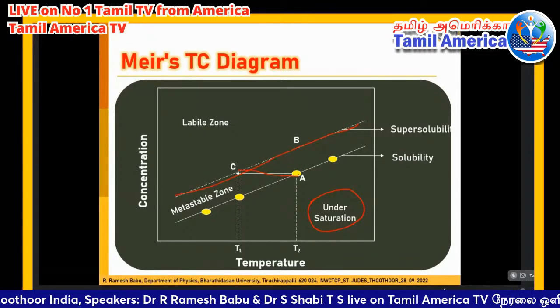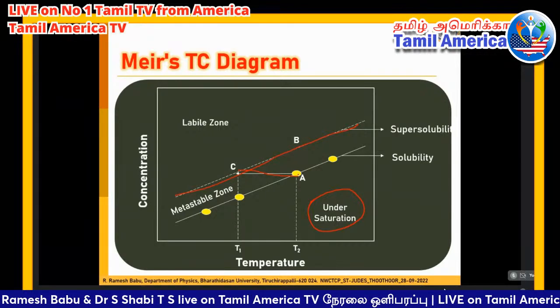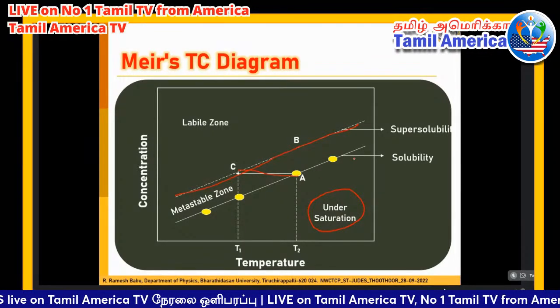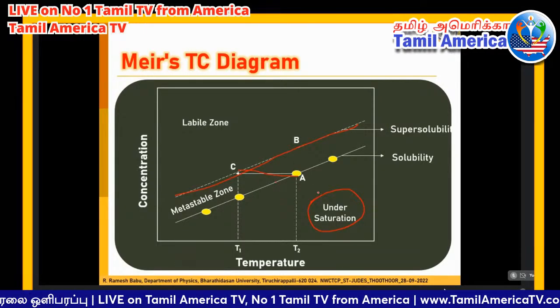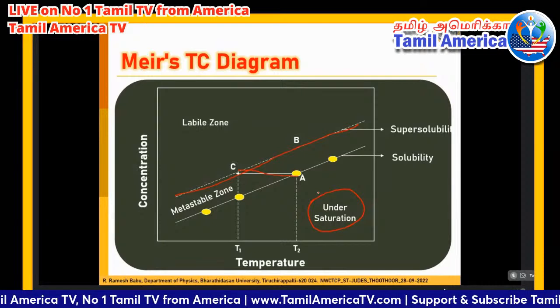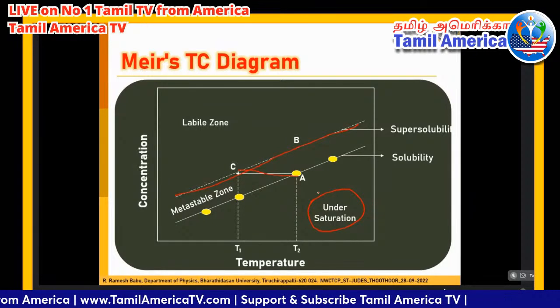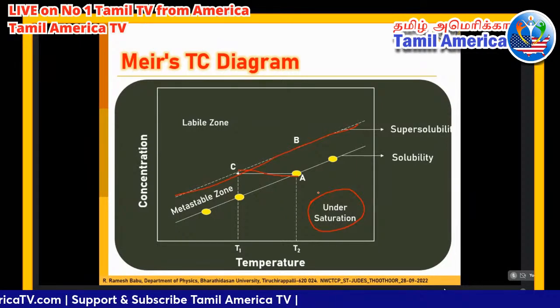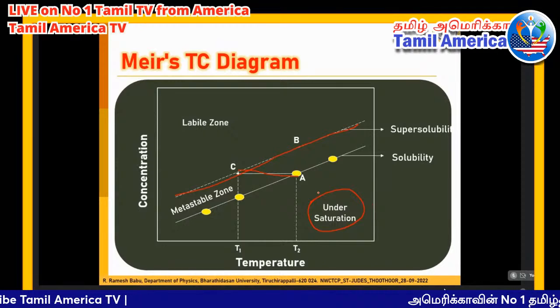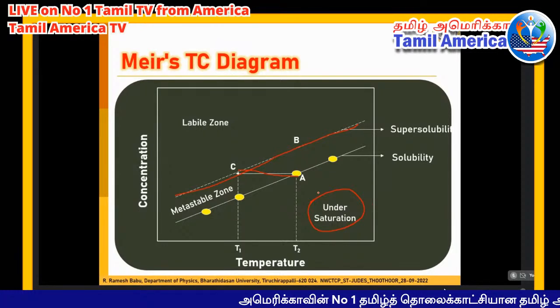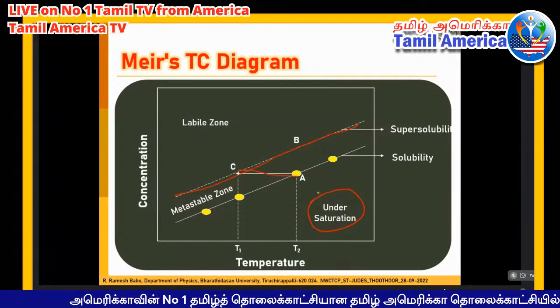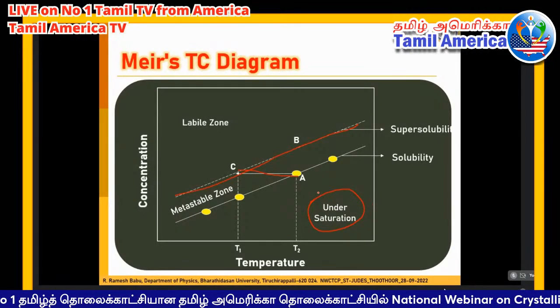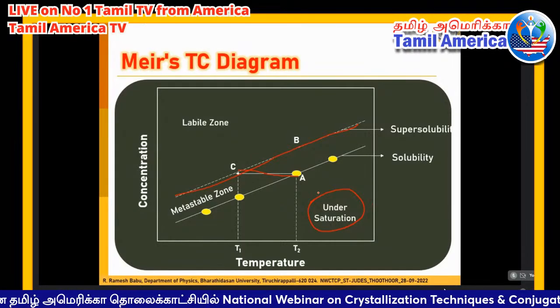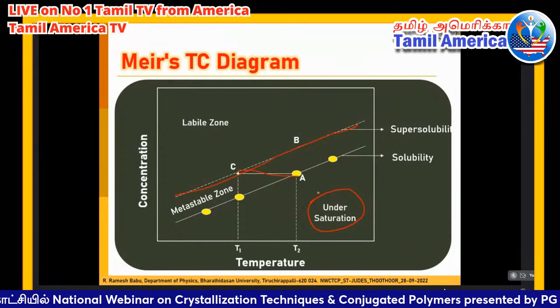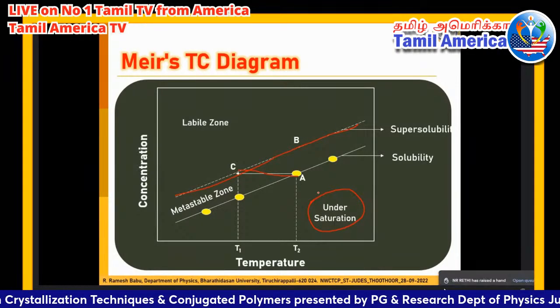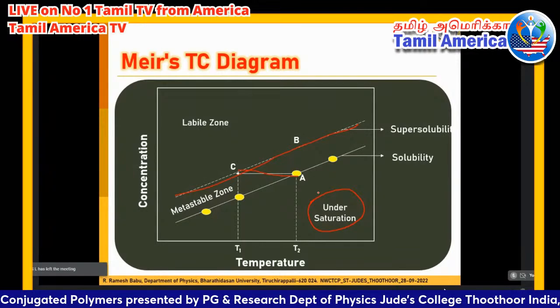In this metastable zone, we can grow very good quality single crystals. When you optimize the temperature between the solubility and the supersolubility of the material, we can get the metastable zone width. Different materials have different metastable zone widths. Before growing single crystals by the solution technique, using this solubility data, we need to understand the metastable zone region, or metastable zone width. For example, for some materials it may be 5 degrees centigrade, for some 2 degrees centigrade, for some 10 degrees centigrade. We need to understand that temperature, then you can start your crystal growth.